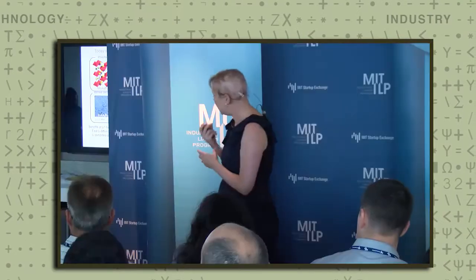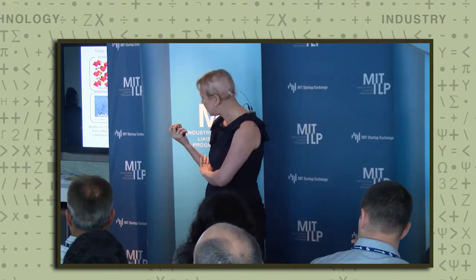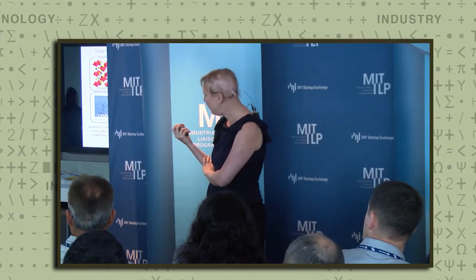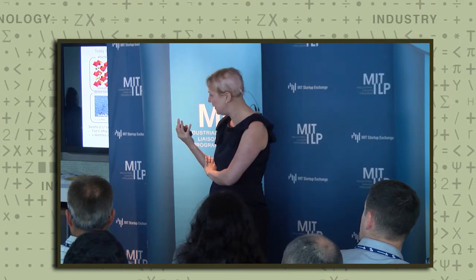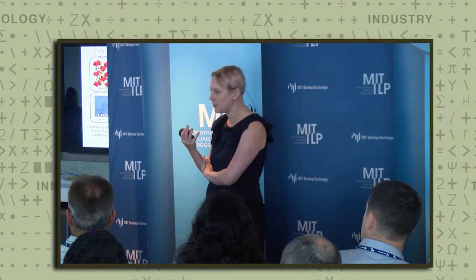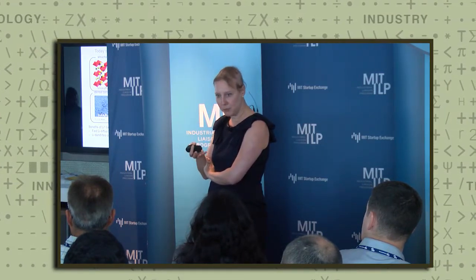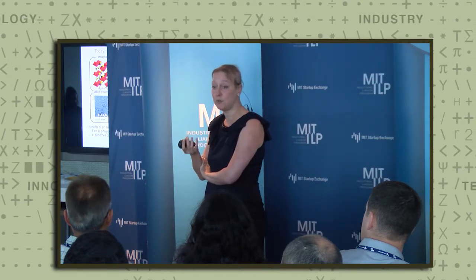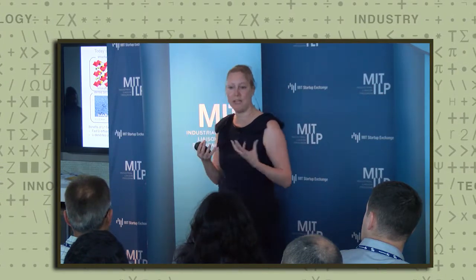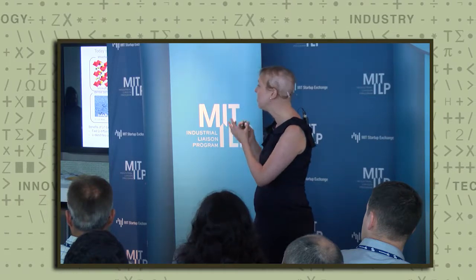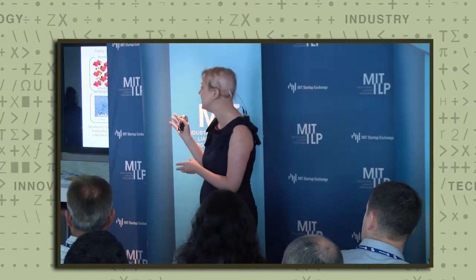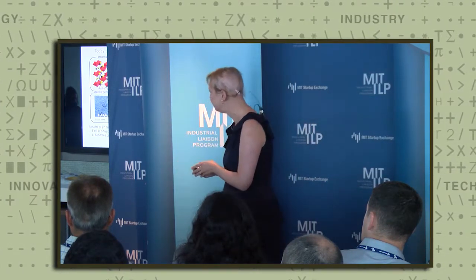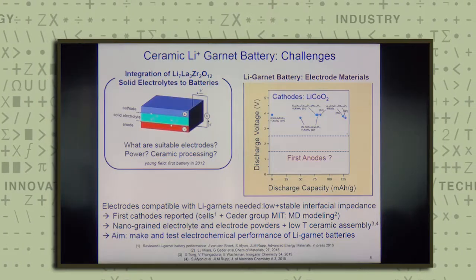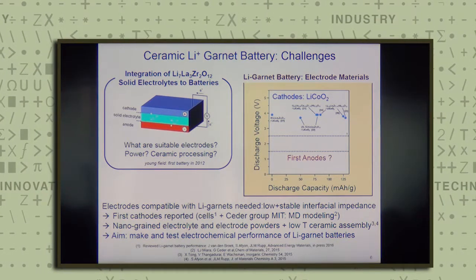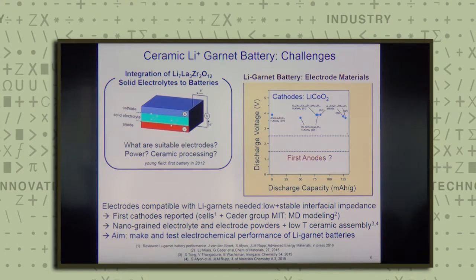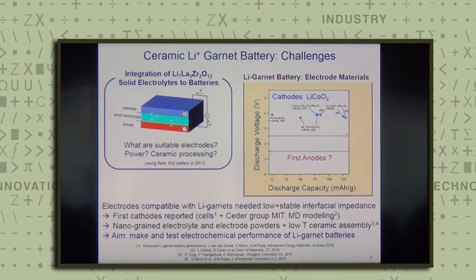So I think the major advantages here are the enlarged temperature operation window, and also that you can, to some extent, use, for instance, electrodes where you don't necessarily have to use pure lithium, and you can also avoid the formation of lithium dendrites, which is often a place for failure in lithium-ion, lithium air, and lithium sulfur batteries. So what has been done on these lithium garnet batteries? Where is currently the challenge if this is among the highest conductive electrolytes to compose such solid-state batteries?